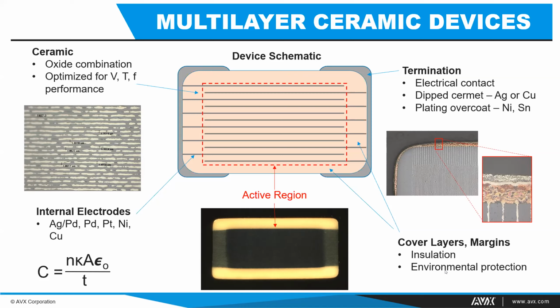I think one thing to point out, though, is because of the proximity of these, the fine electrodes that we have, there's a good bit of stress concentration in the margin regions of the part. And there's also good, fairly hefty mechanical stresses if you think of the differences in shrinkage perhaps between the outside and the inside of the device. So we take care to manage all those kinds of things which are part of constructing an MLCC.